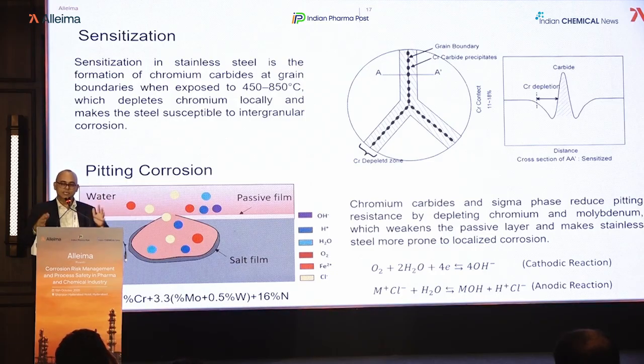You can see that there's an intergranular attack. And then this is the schematic. If you have some, say, sigma phase, that is intermetallics, then what happens is that your passive layer, which basically protects and gives the corrosion resistance to stainless steel, weakens. And if you have chloride in the media, the weaker region gets attacked by the chloride and, of course, by this electrochemical process.